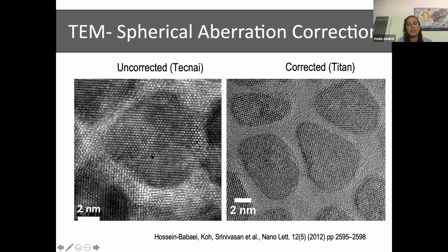So the one thing that you can immediately see is that these white spots that we see on the particle itself are delocalized relative to the background, where here it's clear that the background is an amorphous surface, and you have very clear details and you can see the edge of your particle very clearly. And that's what the aberration correction does for us. So great.